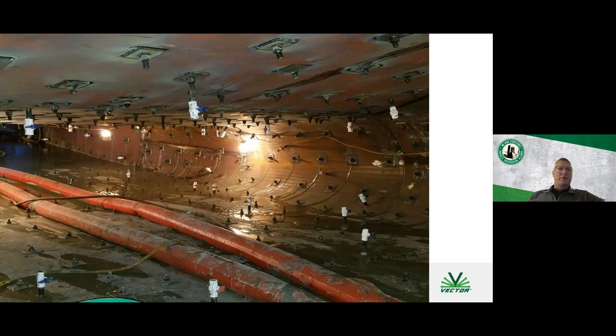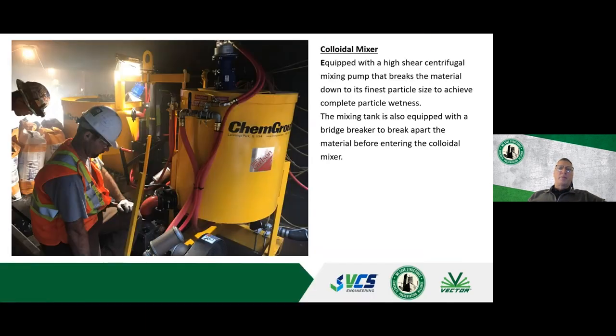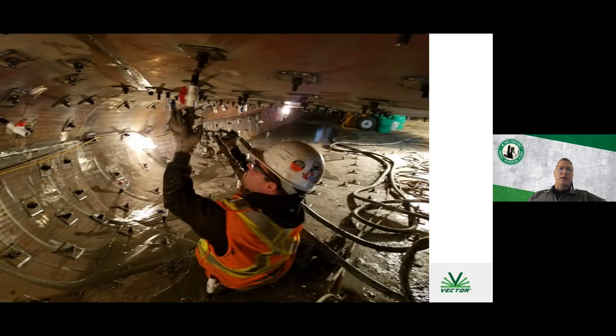Here's a good photo of it. You're holding on, with the steel anchored to the concrete above it, and everywhere you see a white PVC, that's where we were injecting the cementitious material. And here's the grout pump. I put something on here about a colloidal mixer. I won't go into it, but if the data sheet calls for a colloidal mixer, do not skip that step. This is a very expensive mixing and pump system that we had, but it does a phenomenal job. And this is the injection process.